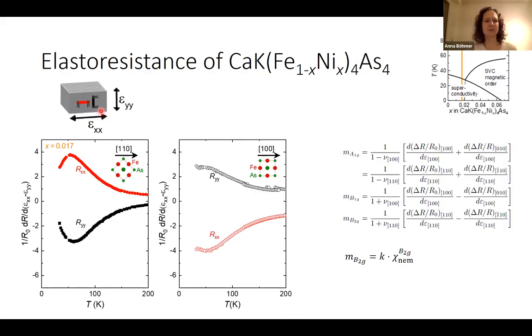And we opted to measure two different crystals that are mounted perpendicularly to each other on a piezo stack, and a pair of crystals for each crystallographic direction. So here I showed the longitudinal and transverse elastoresistance for one specific composition as an example. From this data, you see the coefficients are fairly small. There's a sign change between longitudinal and transverse, another one between the two crystallographic directions. And to obtain the symmetry components of the elastoresistance tensor, the sum, the A1G component, that's basically the sum of the two. And we see, because of the sign change, that will largely cancel out. While the B1G and B2G components, that's the difference of the two, those are the ones we are going to look at. And again, that was an important part of the previous talk, the B2G elastoresistance coefficient is proportional to the B2G nematic susceptibility. That's the one that's related to our stripe order.